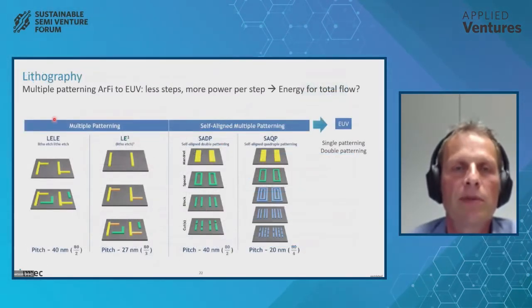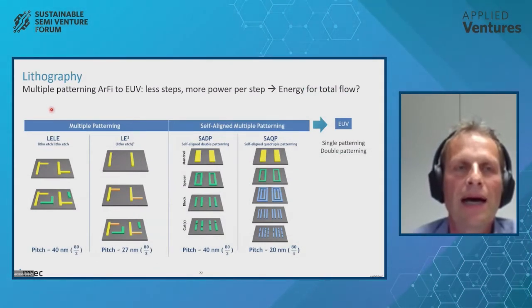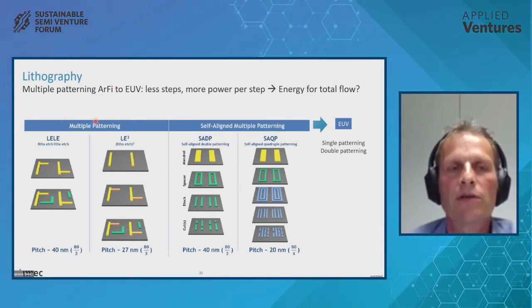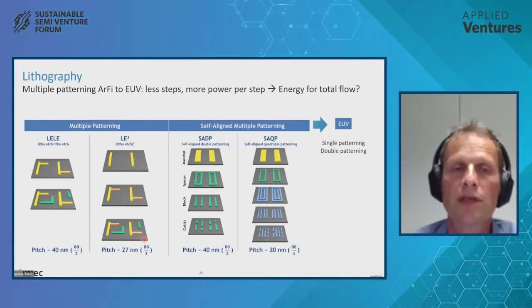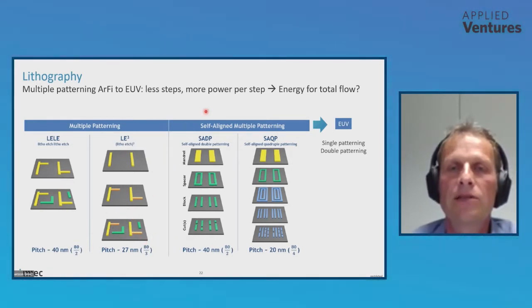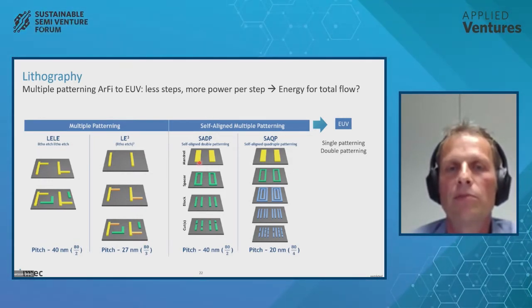Just a very quick word, maybe a bit too technical, about how we do patterning. So actually, using immersion lithography, there were a lot of tricks that were used to enable getting very advanced and tight pitches by doing multiple patterning steps. So you do litho etch repeatedly, or even 3 times, to get to a very dense pattern where the immersion could not get to one print. Self-aligned multiple patterning is similar, where you print something big and then you grow spaces on it and you cut these to enable small feature sizes, and you can do that in quadruple patterning.